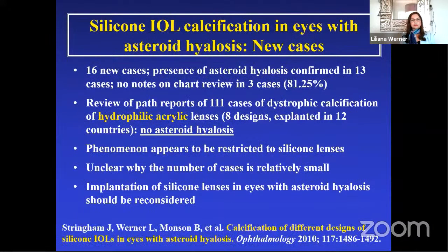The presence of asteroid hyalosis in the eyes in this study was practically confirmed in all of the cases. We also reviewed cases of calcification of hydrophilic acrylic lenses, and we could not find any specific correlation between asteroid hyalosis and calcification. It seems that this phenomenon is really restricted to silicone lenses. It is unclear why the number of cases is relatively small. Maybe there is some underreporting or cases that are not recognized. In any way, implantation of silicone lenses in eyes with asteroid hyalosis can be considered a contraindication.